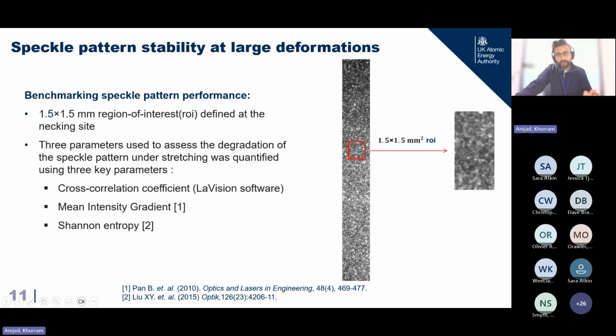The way we do it is we create a discrete layer of black and white paint, and we use polarizers on our DIC cameras to cut down any reflection from the bare metal surface. Because the pattern is discrete, we don't get any significant cracking, even up to 100% extension. So this is what we developed as part of this study. And we did some quantitative analysis using different speckle quality parameters to see if there is any obvious cracking that we can't pick up from visual inspection.